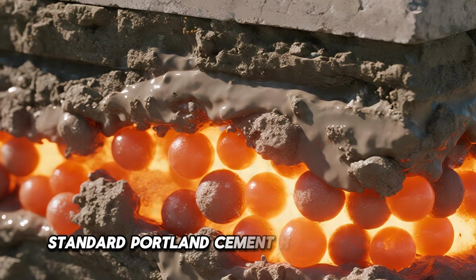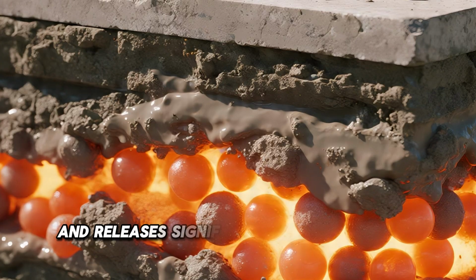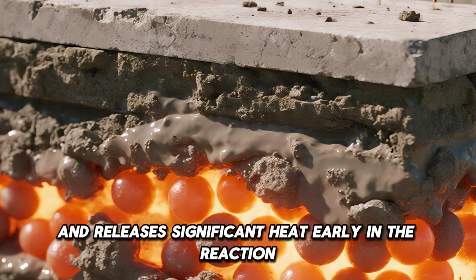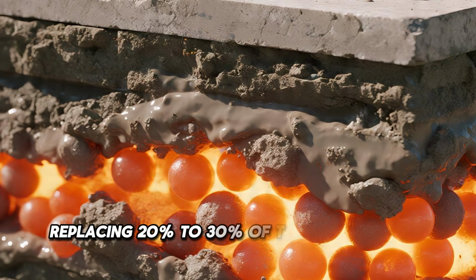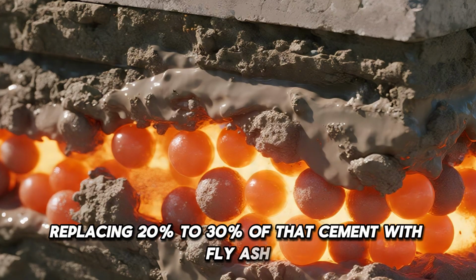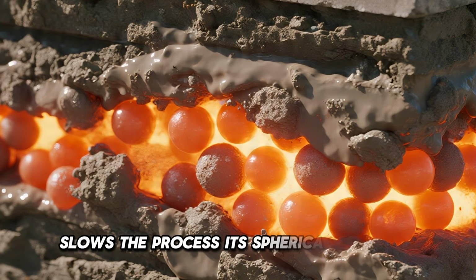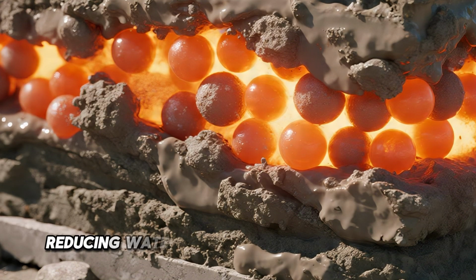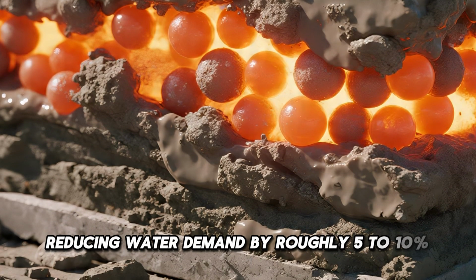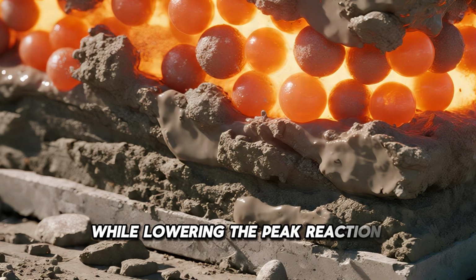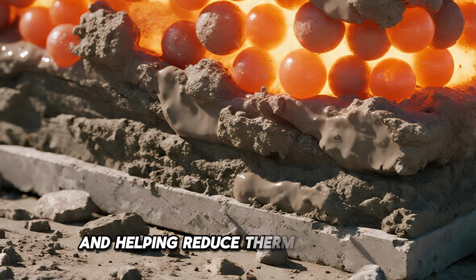Standard Portland cement hydrates quickly and releases significant heat early in the reaction. Replacing 20% to 30% of that cement with fly ash slows the process. Its spherical particles also behave almost like tiny ball bearings inside the mixture, reducing water demand by roughly 5 to 10% while lowering the peak reaction temperature and helping reduce thermal cracking.